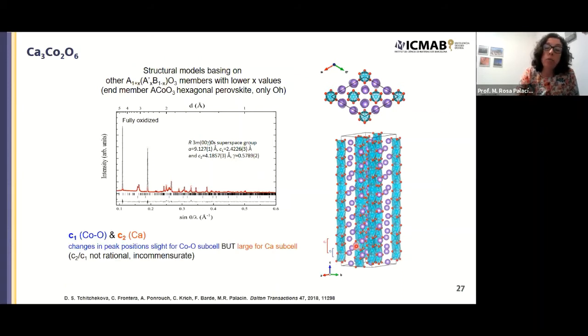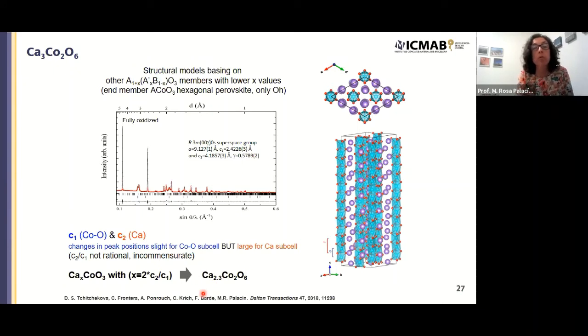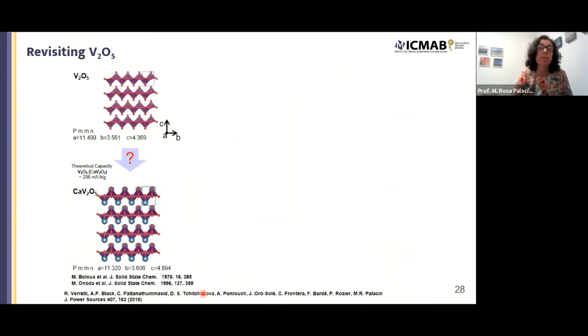And from the Rietveld refinements, we were able to refine the occupation of calcium in the crystal structure, and it was clear that we were able to extract calcium electrochemically. But unfortunately, as I was mentioning, this process is not reversible, at least with the electrolytes we have tested. So coming to conventional intercalation compounds, we were revisiting V2O5.